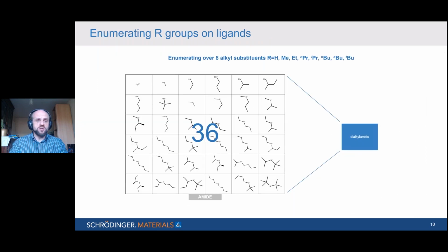So let's just look at one example, an amide, so a dialkylamide, a very simple ligand consisting of nitrogen with 2 alkyl groups attached to it. And if we enumerate over the alkyl groups, we could let them, for example, be methyl, ethyl, n-propyl, isopropyl. Let's just consider 8 alkyl substituents. You could probably dream up a further 8, 10, or 12 easily yourself, but just looking at, say, 8 alkyl substituents on the alkylamide, you already get 36 different possible ligands. And that's just one small family.